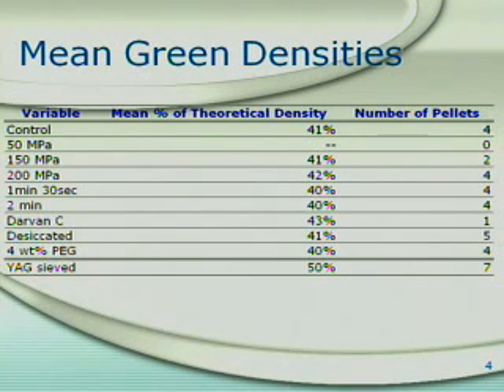5 pellets each were uniaxially pressed at 50, 150, and 200 megapascals, and as the table shows, 50 megapascals was not enough to hold the pellets together. The categories labeled with times show how long I left the load on the pellets during uniaxial pressing. The Darvan C row shows the data for the pellets that I suspended with it. It is used to reduce the agglomeration of the powders and also keep the desired particles from settling out of solution. 5 of the pellets were made just as the controls, but were then kept in a desiccator after being pressed until measurements were made. In another 5 pellets, the amount of binder that was used was doubled to 4 weight % PEG.